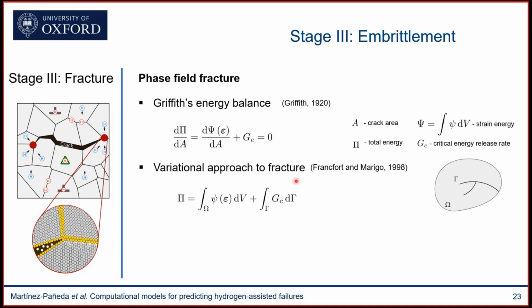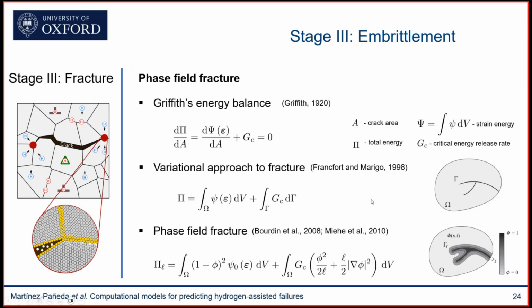However, solving or minimizing this functional is quite complicated for computational reasons, since you don't know where your crack surface gamma is. But here's where the phase field comes to the rescue, because we can use the phase field as a marker, interpolating between intact material points and fully cracked material points, and acting a little bit like a damage variable. You can see here the phase field goes from 0 in intact material points to 1 inside of the fully cracked material points. And it's a non-local damage model in the sense that there's a gradient and there's a length scale, which means that all predictions are going to be mesh objective, so independent of the finite element mesh used, as long as you can resolve the length scale.